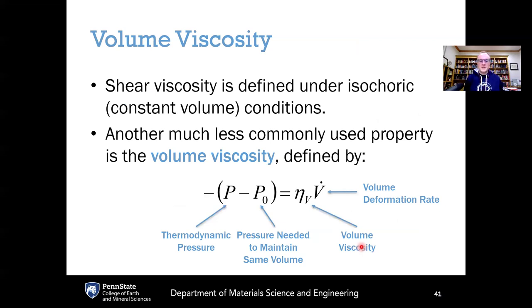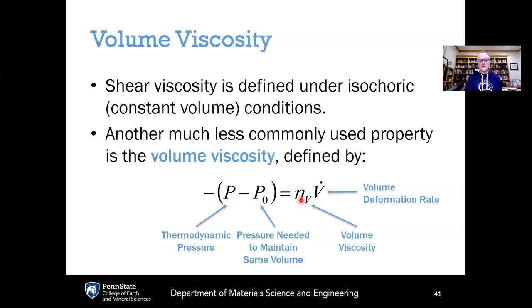Another special topic is volume viscosity. Everything covered so far has been shear viscosity. It is also possible to define a volume viscosity, η_v, which is the ratio between the hydrostatic stress (or applied pressure) versus the volumetric deformation rate. This is the same concept but with triaxial stress — a pressure change versus a volumetric deformation rate — instead of biaxial stresses and strain rates. This is not used very much because it is very difficult to measure, and there is almost no literature dealing with volume viscosity because of that difficulty.